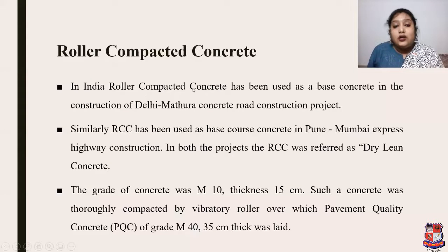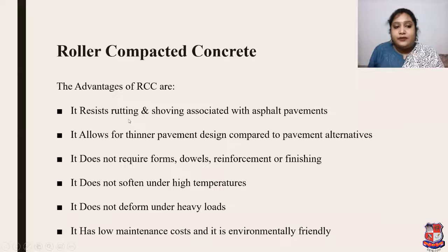In India, roller compacted concrete has been used as a base concrete in the construction of the Delhi Mathura Concrete Road project. Similarly, roller compacted concrete has been used as a base course concrete in Pune Mumbai Express Highway construction. In both projects, the roller compacted concrete was referred to as dry lean concrete. The grade of concrete was M10, where M represents mix, 10 representing its strength in megapascal after 28 days. Thickness 15 cm. Such a concrete was thoroughly compacted by vibratory roller, over which pavement quality concrete of grade M40 and 35 cm thick was laid.